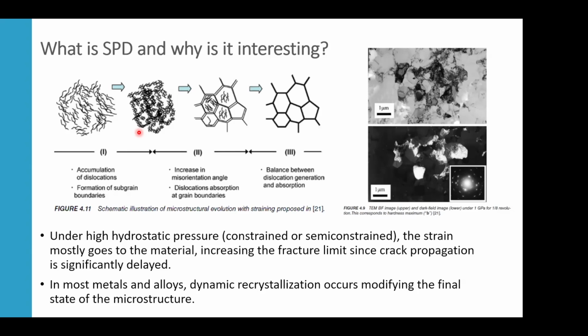So in a wide variety of ductile metals, the grain size can be significantly reduced when you compare it to conventional methods of plastic deformation. And also we can do it to very hard materials and usually get even smaller equilibrium grain sizes. So it's possible to tailor the dislocation density of these materials and also the grain size. And we can also, of course, use heat treatment to further tailor these microstructures.